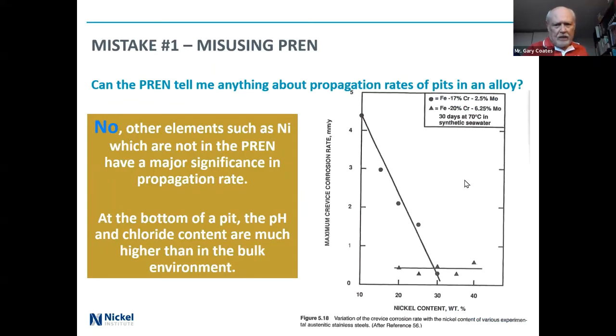And this picture on the right just shows the fact, and it's really the top one where we have the round circles, where we have essentially a 316L type alloy, that the nickel content, as we increase it, will drastically reduce the corrosion rate. Here we're actually measuring it as crevice corrosion, but the environment in a crevice will eventually be the same as what it is in the bottom of a pit. So it's a very comparable way of looking at it.